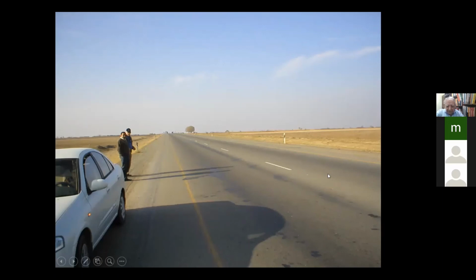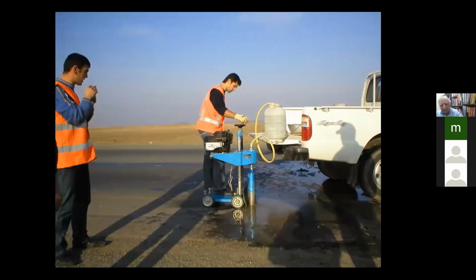This is the construction joint between the 2 lanes, and that can go bad. But why a crack in the middle of the paved lane? That was puzzling them. So this is the crack here. I told them I wanted to take some cores on the crack and away from the crack, and do density measurements, because they put down 2 layers, a surface course and a binder course. So we measured the density of the surface course and the binder course on the crack and away from the crack.